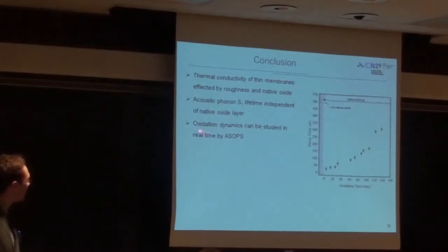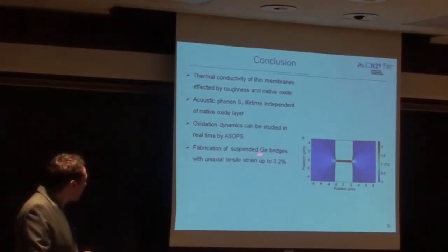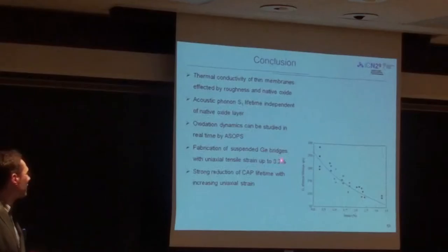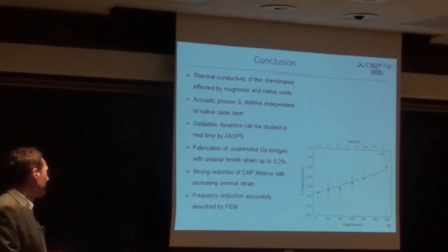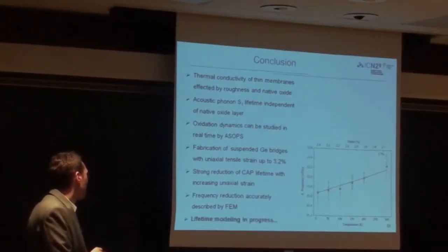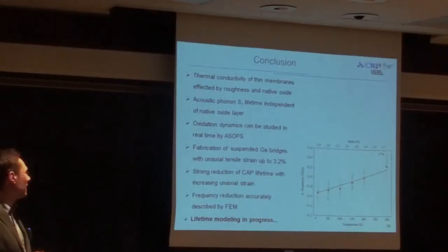You have seen that we can follow the oxidation dynamics in real time, studied by ASOPS. Then I've showed you the fabrication of these kind of highly strained germanium bridges with strain values up to 3.2%. And we've seen the strong reduction of the coherent acoustic phonon lifetime with increasing uniaxial strain. And they follow basically very nicely the frequency dependence. And currently we're trying to understand this kind of lifetime dependence.